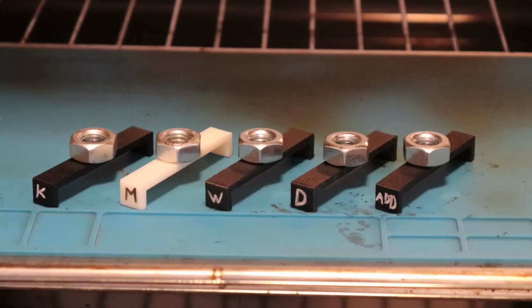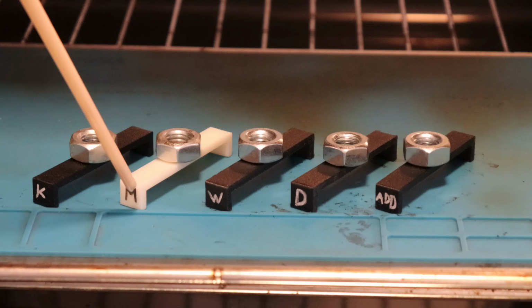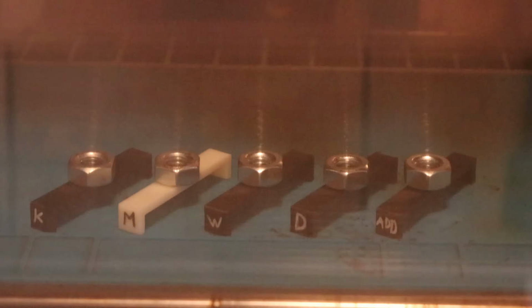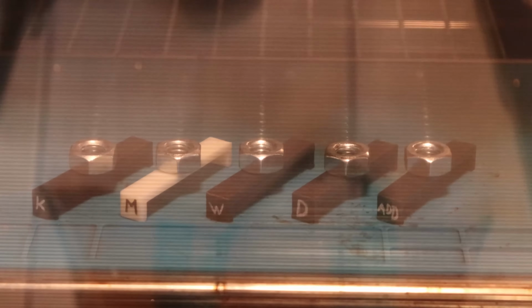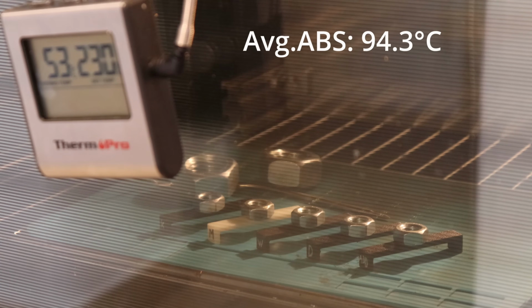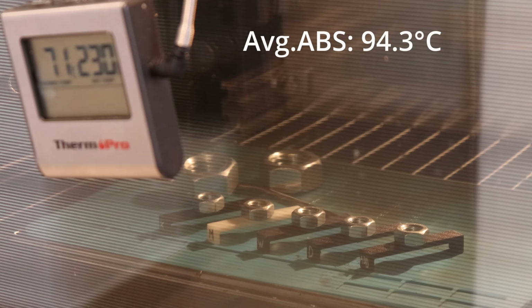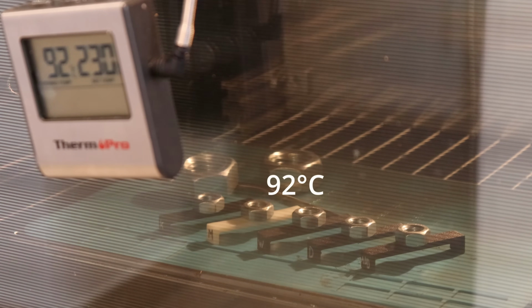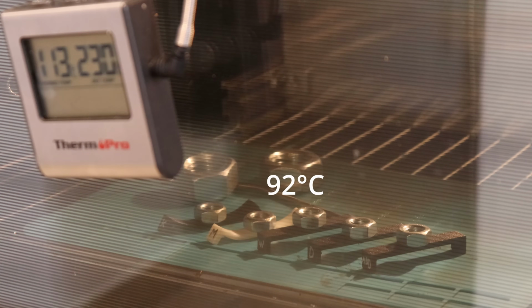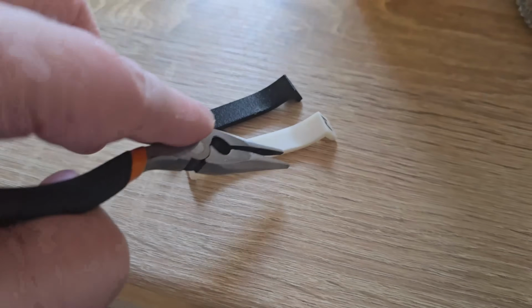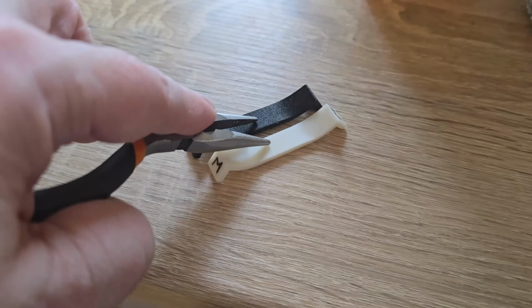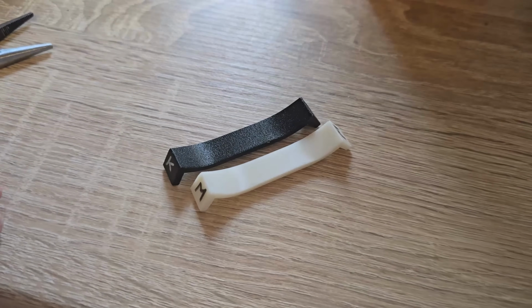Temperature test in the oven, and this is the filament from this video. I want to record the temperature of the first noticeable deformation. For the average ABS, this is 94.3 degrees Celsius, and this was quite close to 92 degrees Celsius. And when I stopped the experiment, after 30 seconds, it was quite hard already.